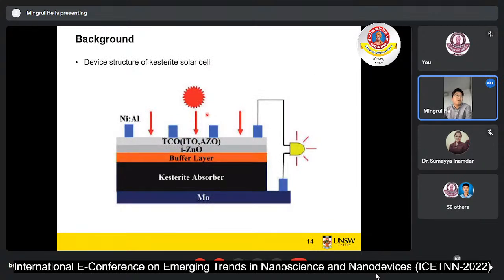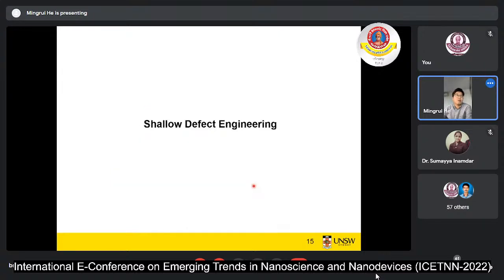Before starting my topic today, I would like to introduce what the device structure looks like for the kesterite solar cell. The back contact is normally molybdenum. Here is the kesterite absorber and the N-type buffer layer, and we use the intrinsic ZnO and the TCO, like ITO and AZO. We deposit the metal contact for the working of the solar cells. So here is the first work, for shallow defect engineering.